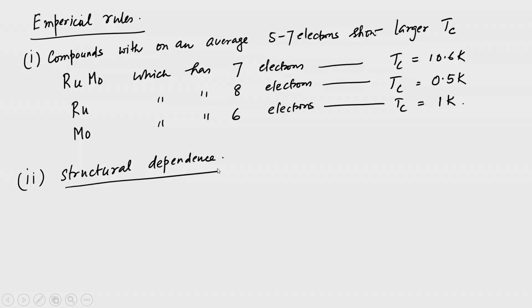And when these studies of the structural dependencies were done, they found that there are structures such as the A15 crystal structure, which is also called the beta tungsten structure, that has a higher TC, or all these structures have higher TCs. Let us see what an A15 or a beta tungsten structure looks like.